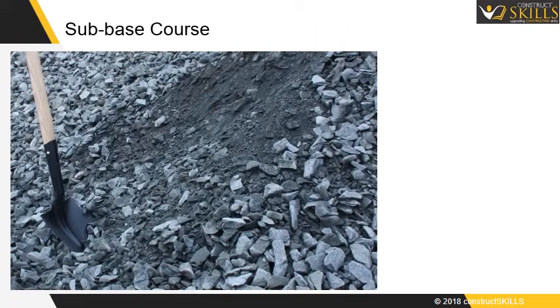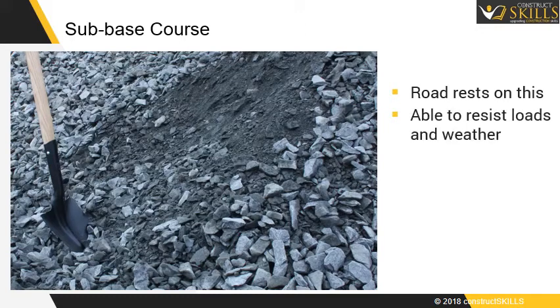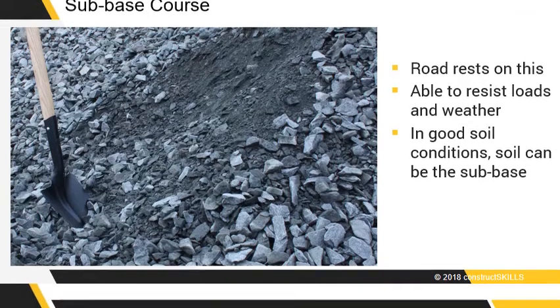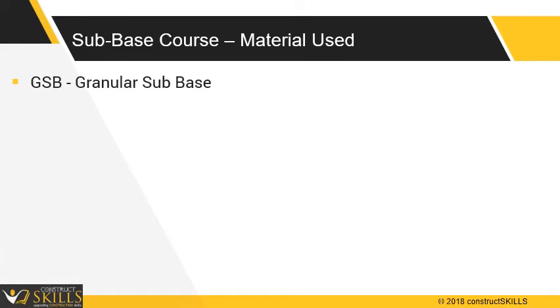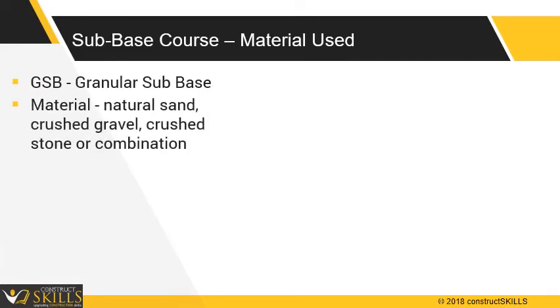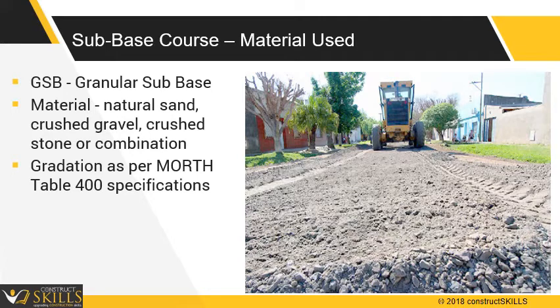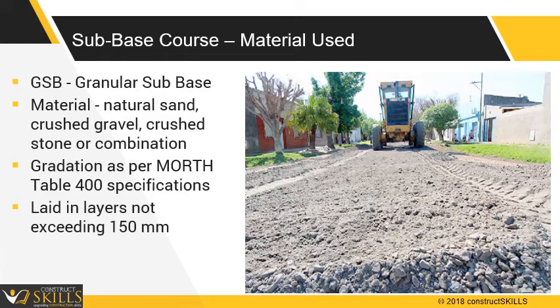Sub-base course: the entire road rests on this layer. It must be able to resist loads, weather, and subsurface water. In good soil conditions, soil itself can serve as the sub-base. In recent years, sand or GSB — granular sub-base — is used. GSB is made up of granular material, usually natural sand, crushed gravel, crushed stone, or a combination of all. The material should meet gradation properties as per Morth Table 400 specifications, and should be laid in layers not exceeding 150 mm.